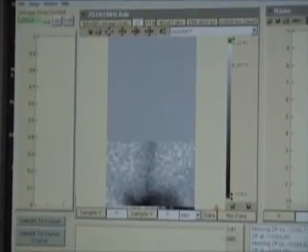Using the very small beam we have, we are scanning a region point by point at one specific photon energy. Then we slightly change this photon energy and scan the region again. This is repeated many times, so at the end it gives us a set of images of the same region but at different photon energies.